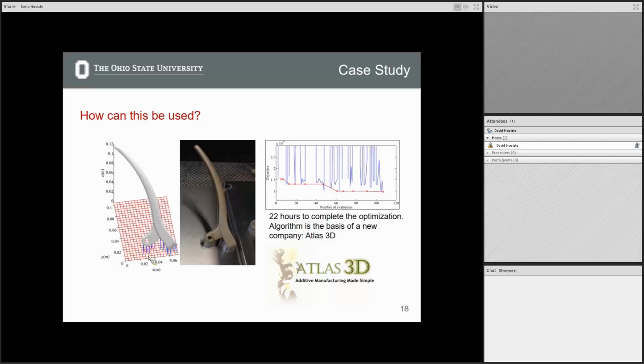And what it's doing is it's reducing the cross-sectional area of any given layer. So we know that the residual stress is going to cause, when it cools, thermal contraction at that top layer, and that amount of total deformation is going to be proportional to that cross-sectional area. And so what this is doing is actually finding an orientation in which it has minimal cross-sectional area. It's also finding one which is minimally constrained.